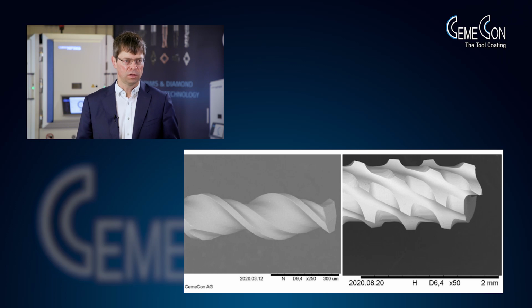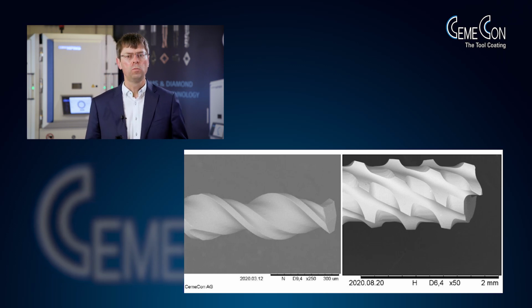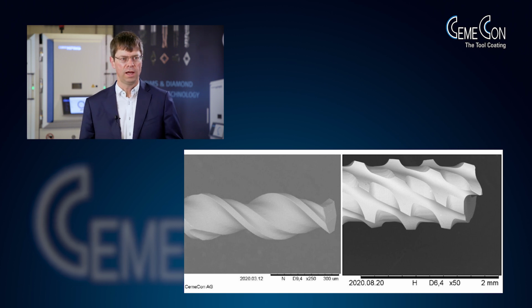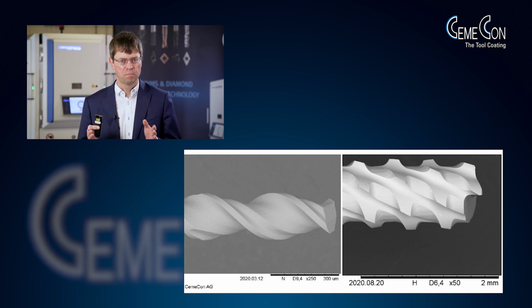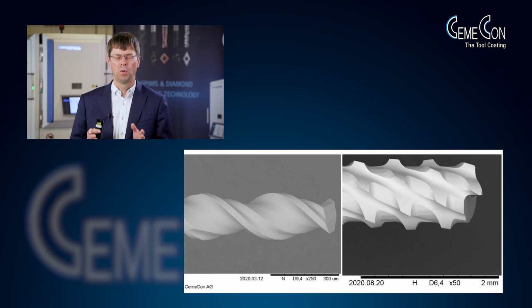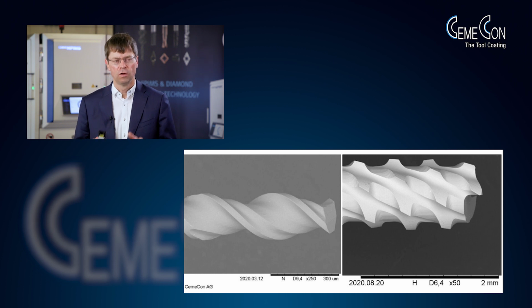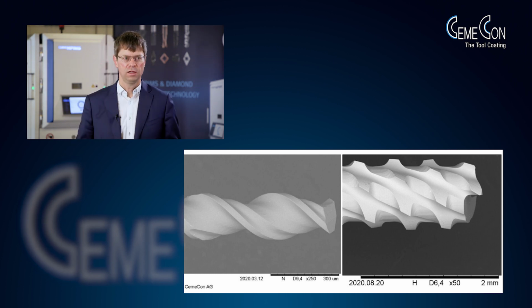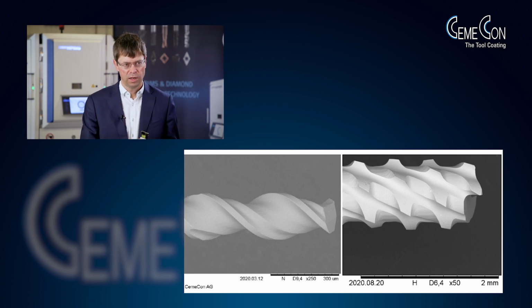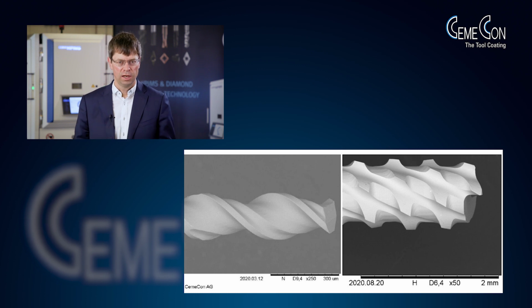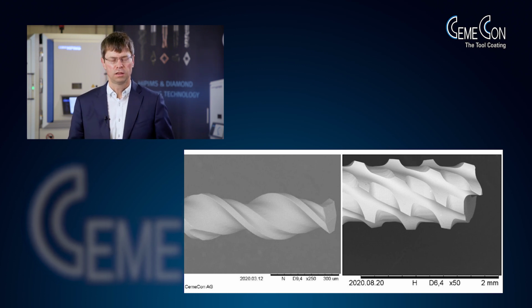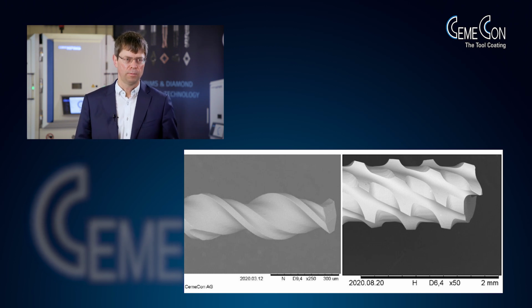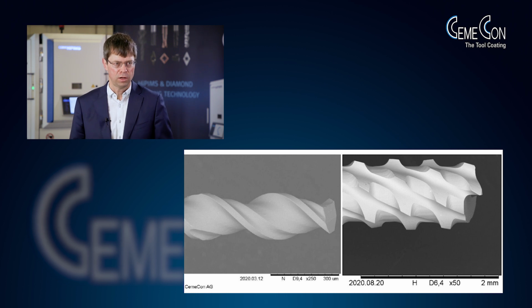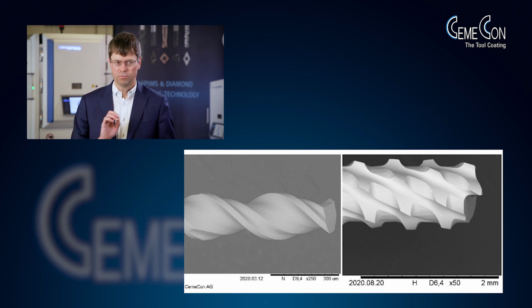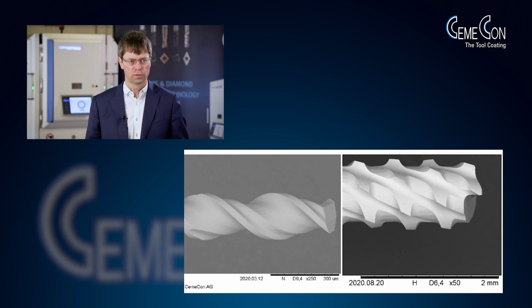Here I prepared on the left-hand side a micro drill, diameter 0.2 millimeter. It's already an art grinding such a tool, quite challenging in coating. And the good thing in this pulse technology HiPIMS is that you have more parameters to tailor the energy for a certain object. You have not just the pulse height, you have also the pulse length and the relation between on and off time. So you can tailor the energy precisely to an object like this very small drill with very sharp edges. And what you see here in the scanning electron microscope image: perfectly coated surface, perfectly coated primary and secondary cutting edge.